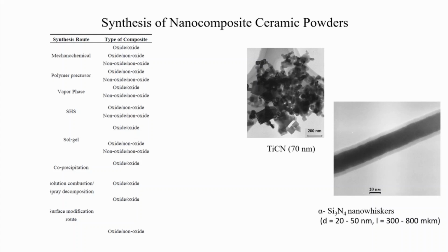When designing a composite structure, it's essential to consider not only the chemical composition of the matrix and second phase, but also the quantity, distribution, and morphology of the reinforcement phase. One critical aspect is attaining a uniform distribution of the second phase within the matrix material. However, this remains a challenge, especially when using nanocrystalline particles, due to their exceptionally high specific surface area and thus a natural tendency to agglomerate.